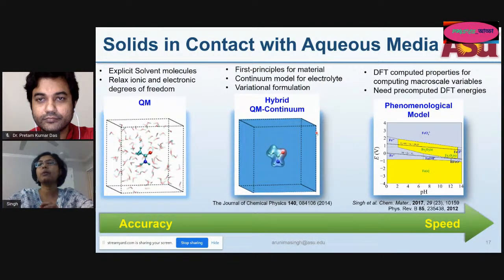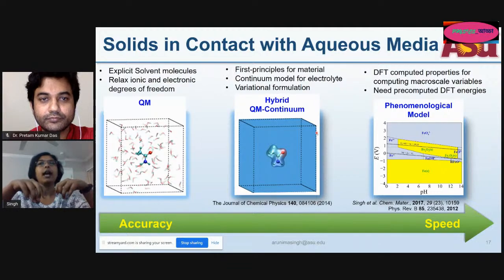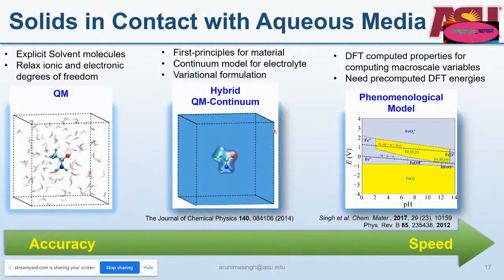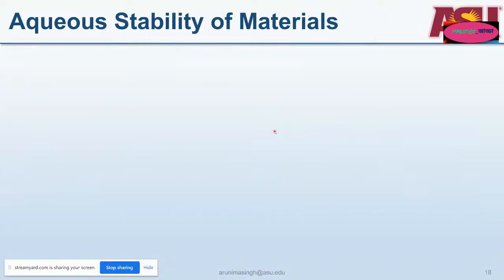What we decided to do was go with identifying a method based on a phenomenological model where you use DFT computed energies to make these electrochemical stability maps, which I'll describe in a bit, which can tell you about the stability of metastable materials as a function of potential and pH. Okay. So what is this phenomenological model, and how does it help in assessing the aqueous stability of materials? Before we go there, let's go very simple. Let's just look at what happens if I place something in water.